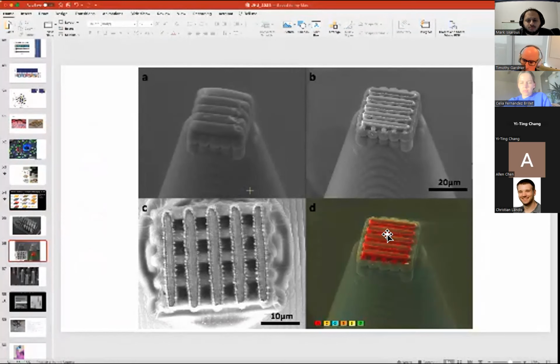You can see here on an EDS, the platinum signature is in red, so there's platinum metal that's exposed after that laser ablation. And we just thought that adding that little bit of microstructure on the tip of the electrode would increase the surface area for the metal and lower our impedance.